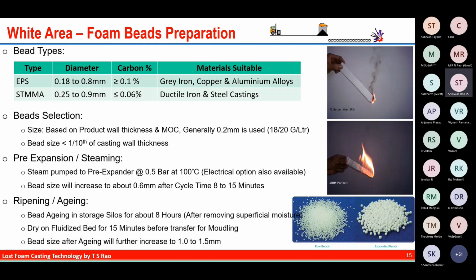Dry on a fluidizer bed for 15 minutes before transferring for the molding. Again we have to dry, and only dry, expanded, ripened beads are given for the molding. Bead size after the aging will increase to 1 millimeter. Here you can see 0.2 become 0.6, 0.6 become 1 millimeter.